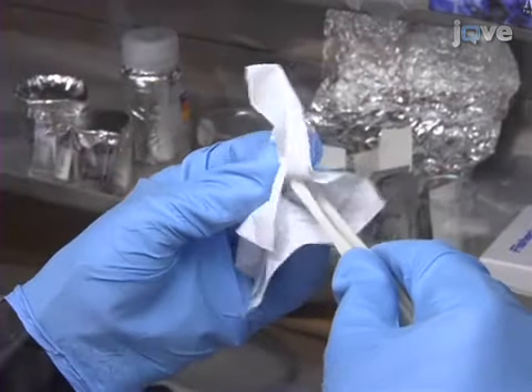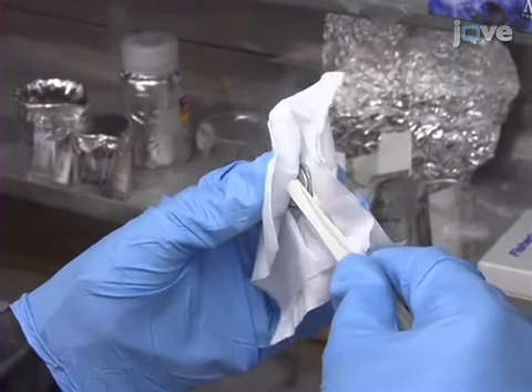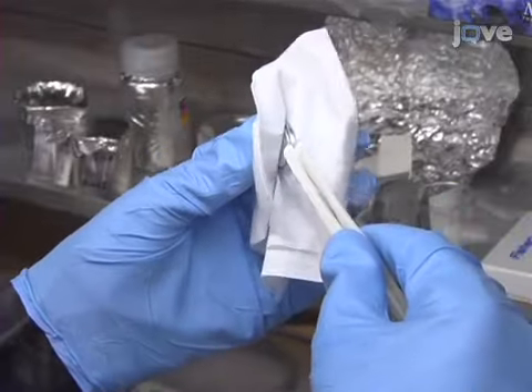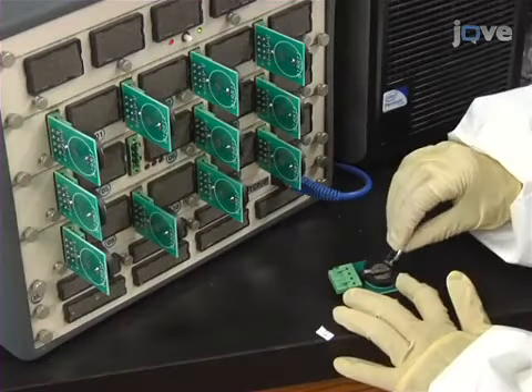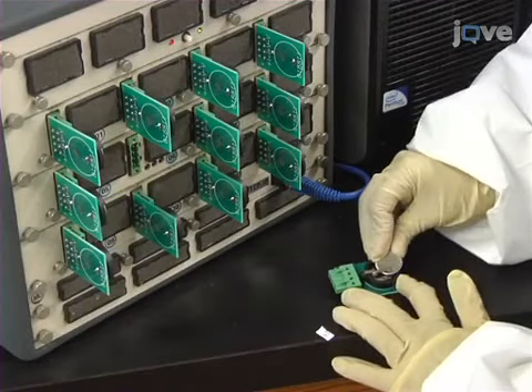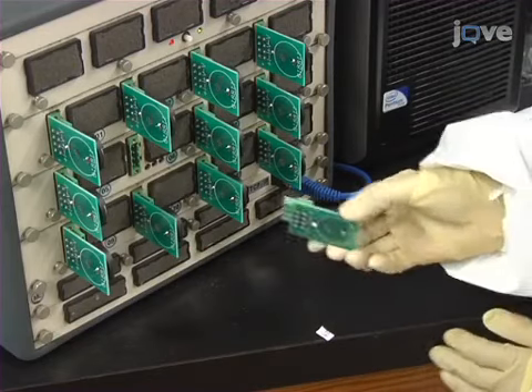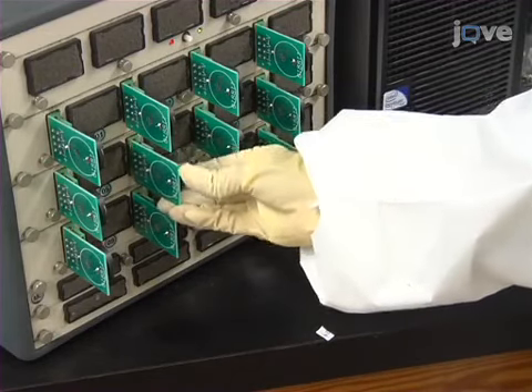Handle the finished cell with plastic tweezers to avoid short-circuiting and wipe off the excess electrolyte. As soon as it is assembled, connect the coin cell to the battery tester in the open circuit voltage mode for 1 hour.